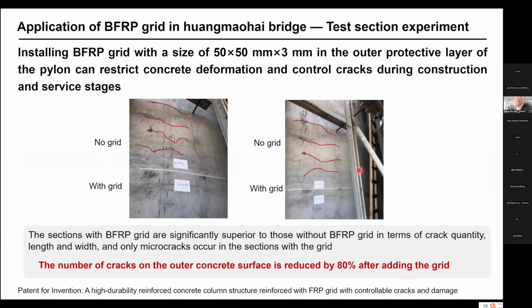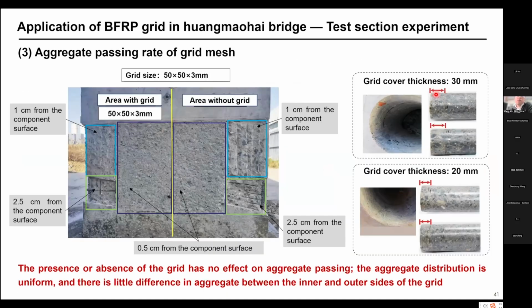And this is an on-site observation. Okay, so with the grids, no cracking. But without the grids, it shows very clear cracking. Also, because this grid has a spacing between each strand, it allows the aggregates to go through. This is a sample from the testing, and you can see the aggregates can go through the grids very well. It will not affect the property and uniformity of the concrete.